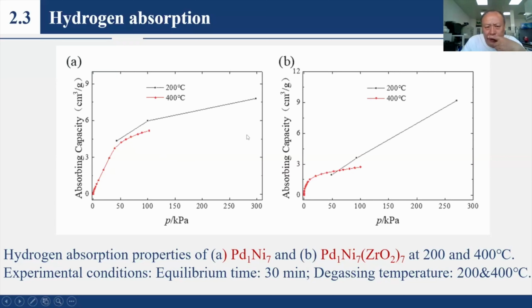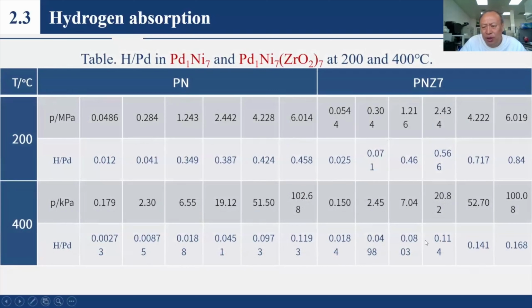All the results indicate the hydrogen absorption is mainly by palladium. Whether it is palladium-nickel or palladium-nickel-zirconium, actually only the palladium absorbs the hydrogen. This is the calculated result of the loading ratio, H over Pd, and this result is consistent with pure palladium metals.